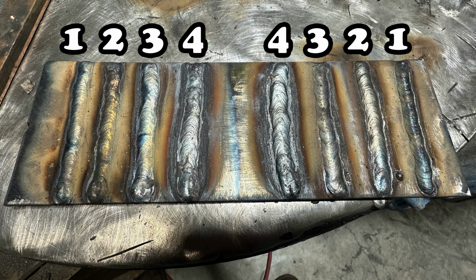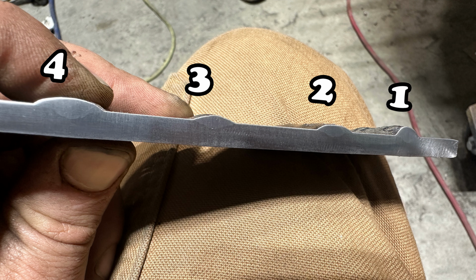We'll start out with my side, which is on the left there. So the coldest weld was the number 1, and number 4 was when the plate was super hot. There's a couple things that we can determine from this. One, as the plate got hotter, the welds tended to spread out more, so much wider. And I can tell you, actually welding these, that when I got up at that 1,000 degree one, more or less, it just seemed like a pool of molten metal was flowing out flat.